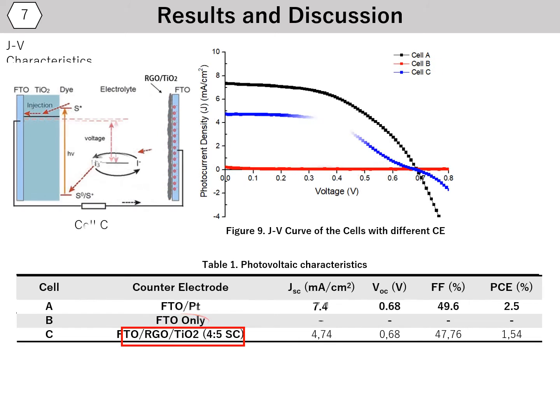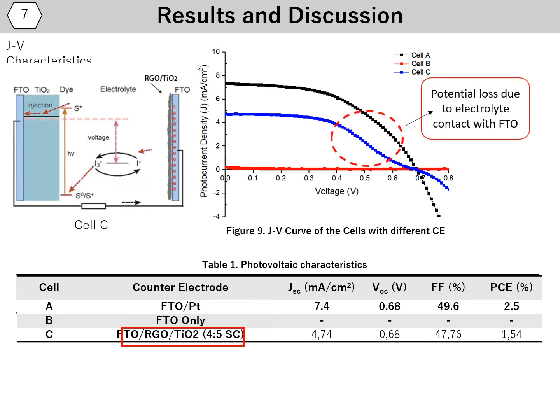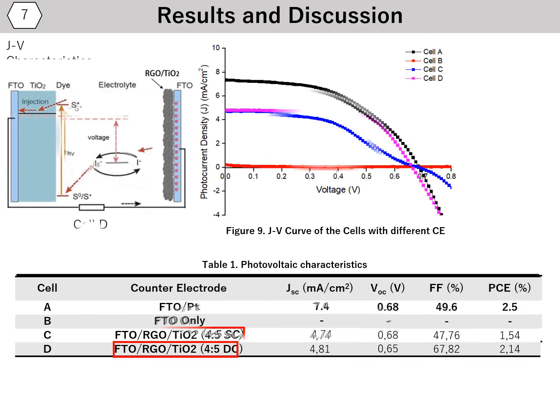Meanwhile, when the counter electrode is RGO titanium dioxide composite in film with spin coating deposition, its photovoltaic characteristic has lower performance than cell A, and showing a shift. It may be due to the electrolyte species contacting the FTO substrate and possibilities for potential loss. Compared with the counter electrode using RGO titanium dioxide composite in film with drop casting deposition, it shows a JV curve with quasi-square shape. It's predicted that cell D has lower recombination loss than cell C, since the film, which is deposited on the FTO substrate, is thicker and inhibits electrolyte species reaching the FTO substrate.